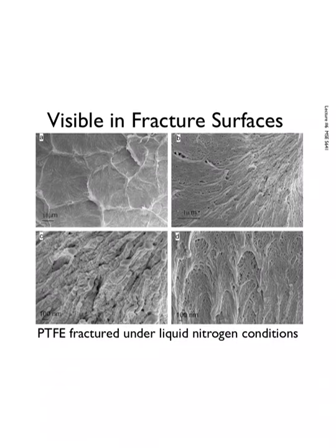But with polymers, you can't really get much out of fracturing polymers. Even if we do what's suggested here, you take it and cool it down into liquid nitrogen conditions, which is only 77 kelvin, polymers still move around pretty well at that temperature. So we don't really get brittle fracture with these polymer-based systems.